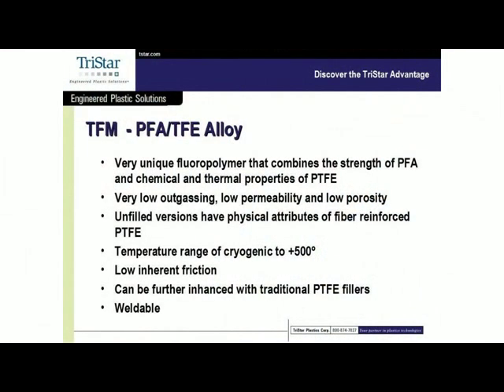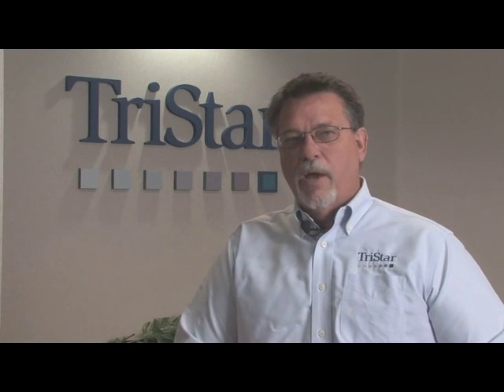The temperature range, because of the PTFE component, it's very, very close to PTFE. It's cryogenic up to 500 degrees. So very solid material across the full temperature spectrum of fluoropolymers. Friction is very low, not quite as low as PTFE, but pretty good. Again, as a release material, inherently, no additives, has pretty low friction properties.